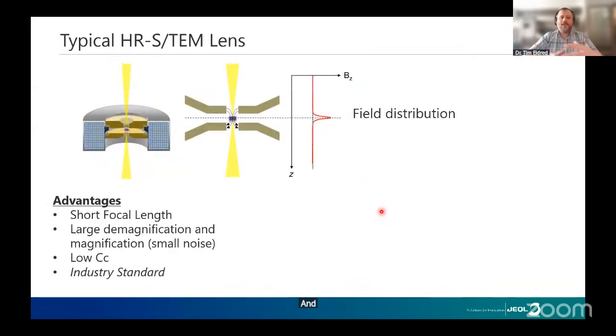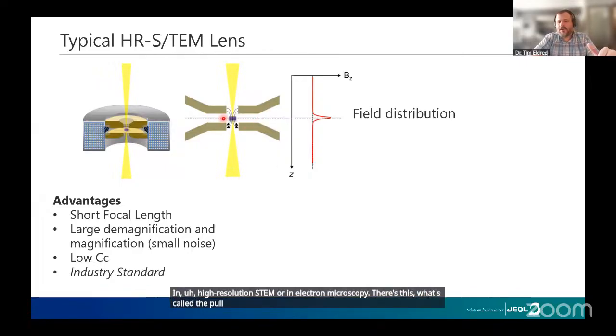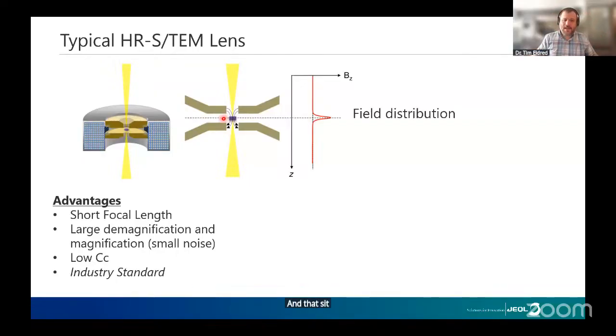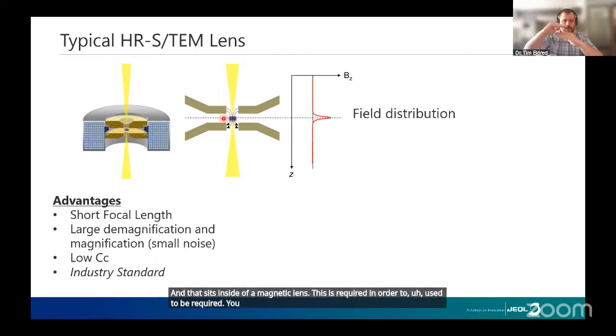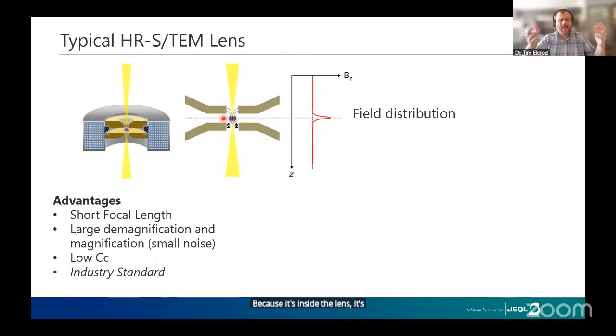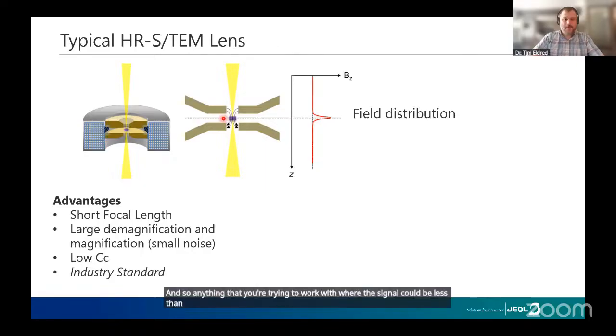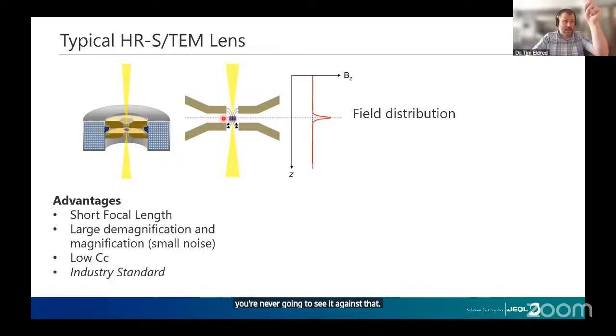And the reason for that is typically in high resolution STEM or in electron microscopy, there's what's called the pole piece that your sample sits on, and that sits inside of a magnetic lens. This used to be required. You'd have to have a short focal length because it's inside the lens. It's hard to get shorter than that. It allowed for very large magnification, very low aberrations. It's kind of the industry standard. The problem is that that is a magnetic field on the order of 2 Tesla. And so anything that you're trying to work with where the signal could be less than that, you're never going to see it against that. It's like looking at a candle in front of the sun.